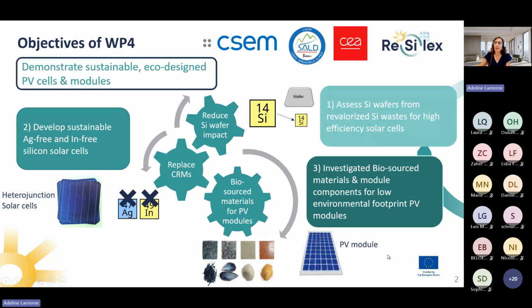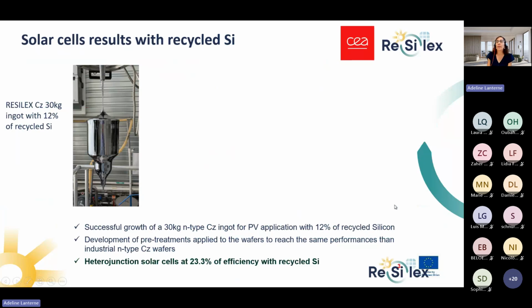And for this, we were 3 partners in the project, CSEM in Switzerland, LMGP laboratory in Grenoble in France, and CEA in France. So first, a few results we had at CEA on the recycled silicon part. Here we have the picture of an ingot that was grown at CEA in the project. So it's a 30 kilogram Czochralski ingot, where we incorporated 12% of recycled silicon produced at NTNU University in Norway in the project. So it's a silicon which is very particular because it was processed with a low CO2 emission process and using revalorized silicon waste.